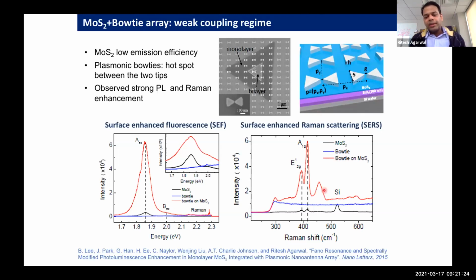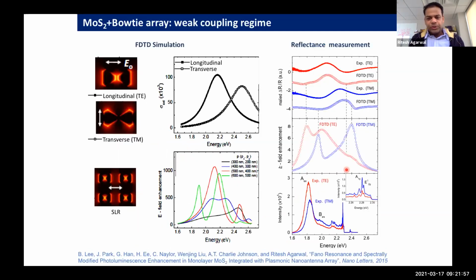Okay. So our first effort, this was some time back, was an array of bow ties, where the idea was that between the two apexes of these triangles, one can confine fields very strongly. And if you have a lattice, then one can engineer a lattice mode. By engineering this lattice mode, one can increase the quality factor of the plasmonic modes. By doing so, our first efforts led to very strong enhancement of the emission and the Raman scattering via the Purcell effect.